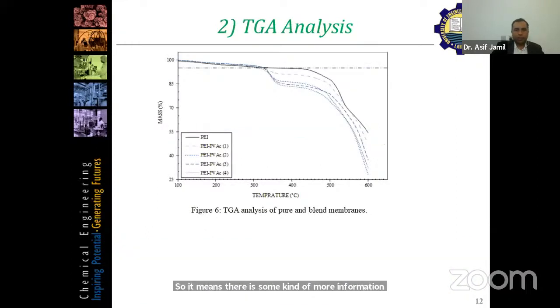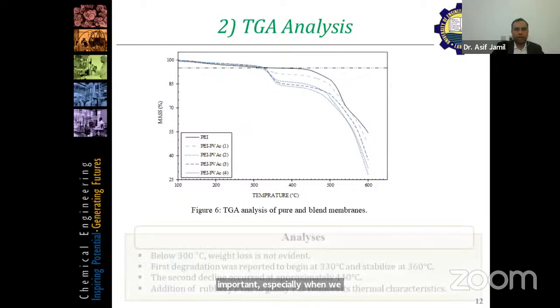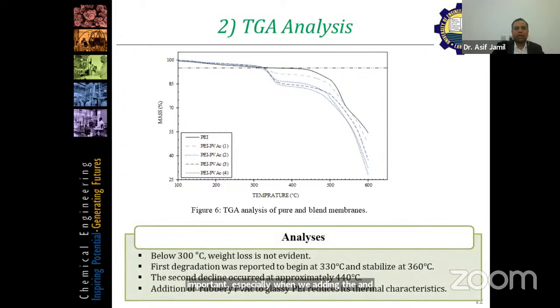And the thermal properties are very important, especially when we are adding rubbery polymers. So as expected, there is no weight loss below 300 degrees Celsius, but from 330 to 360, we have some degradation, and we have a second decline at approximately 440 degrees Celsius. So one thing is very clear.